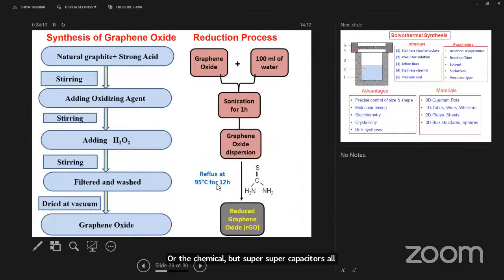And this is actually the simple chemical reduction process by which graphene oxide can be prepared and then converted into graphene or reduced graphene oxide. We take natural graphite as the source material and mix it with very strong acids. Then we deliberately introduce the oxygen functional groups by adding an oxidizing agent. After filtering and washing, we dry it in vacuum to get graphene oxide. The graphene oxide can be mixed with water, and after sonication for about 1 hour, we get the graphene oxide dispersion. To reduce this dispersion, we use a proper reducing agent.